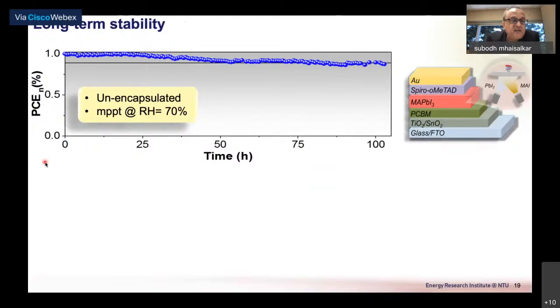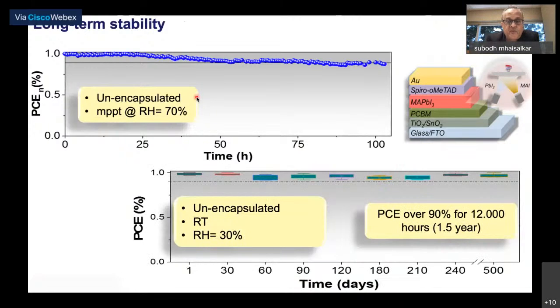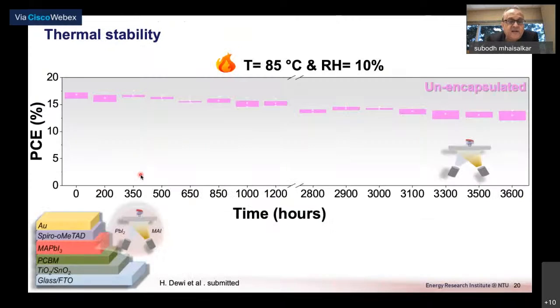And all the data I'm showing you today is materials which do not have any encapsulation. So these are unencapsulated solar cells. And what I'm showing you in this graph is solar cells that have been held for more than 100 hours at MPPT with a relative humidity of 70% in our environment. We also studied unencapsulated cells at room temperature and a slightly lower relative humidity. And here we have studied cells that have really been held for more than 500 days and with PCEs of over 90%. As I'll highlight to you later on, this is really a special factor from an intrinsic stability of evaporated perovskites. But I'll come to that in just a minute.